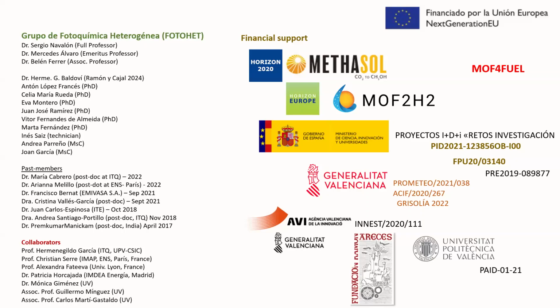Can you further increase the loading of ruthenium oxide and obtain even higher activity? Because you showed that the highest activity was observed for 10% of ruthenium oxide. Normally, we would like to maintain the weight percentage from 1 to 5%. So we have reached up to 10 weight percent just to increase the activity, but upon increasing the weight percentage to 15 or 20, the activity was similar, or even a little bit lower. Because of the particle size, there was a limit. After 10%, the particle size was slightly bigger, and it was also occupying the pores, and the activity was not very high. So then we decided to stop at 10%, because this was the optimal value.